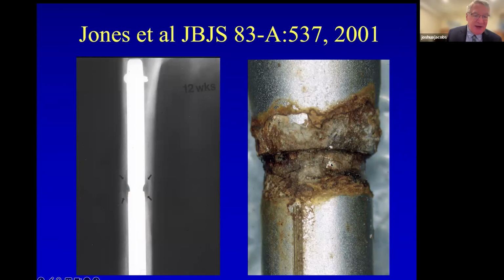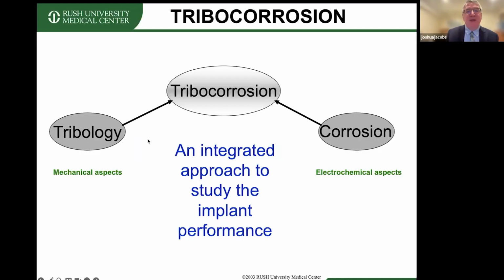The idea was if you had a modular nail, you can minimize inventory and save on costs. Well, it worked in terms of healing the fracture, but it caused other problems with periprosthetic bone loss. So what we didn't know at the time we introduced the metal-on-metal bearings, we did a lot of hip simulator studies, but we only looked at the tribological or mechanical aspects of the interaction between the surfaces. We essentially ignored the electrochemical interaction, and it's really this combined mechanical and electrochemical, or tribocorrosion, system, which is an integrated approach to study the performance of metallic surfaces. We didn't do it at the time, and we suffered the consequences.